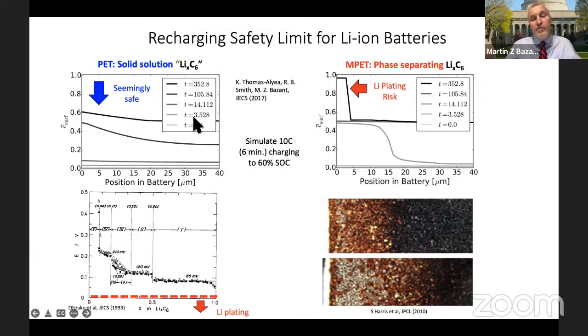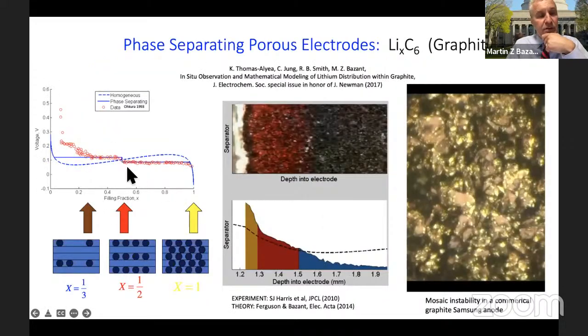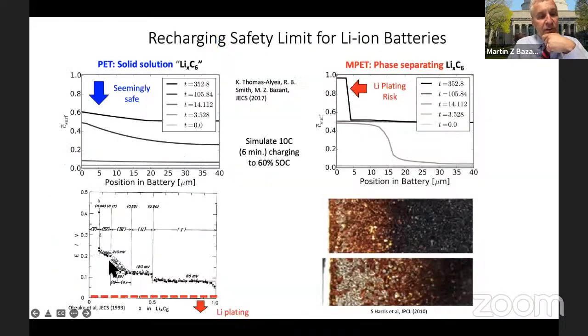So what it means is the battery charged kind of uniformly, and you don't really see any reason to have a problem. Now, why would there be a problem? I forgot to mention here, actually it's on this slide, I showed you this voltage staircase here. The 0 is lithium metal. And what that means is if the potential falls below 0, then lithium electroplating, making metallic lithium, becomes thermodynamically favored, which is a big no-no for lithium-ion battery.